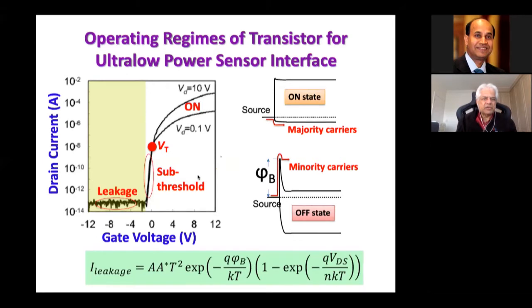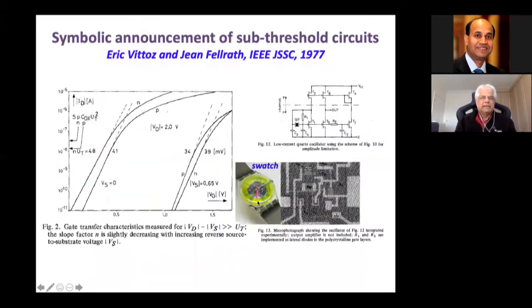And this is true only for wide bandgap semiconductors. If you took silicon, a silicon sensor interface would sit somewhere here, 10 to the minus 11 at best, or maybe 12. So that's like 8 orders of magnitude higher. And if you look at off currents, it's exponential with the band gap. That's the reason you're able to get such low values compared to what you get in silicon. Now, this is nothing new. We looked at it at the thin film transistor level, but people have used subthreshold circuits from the 70s.